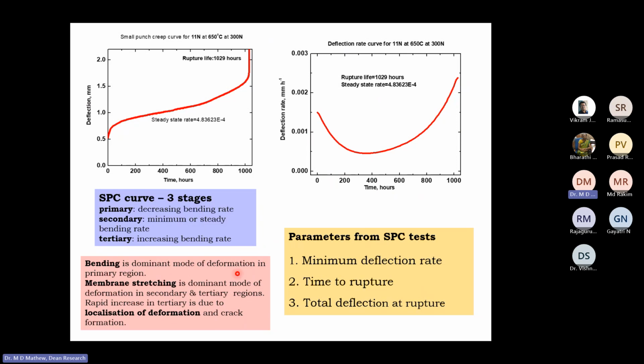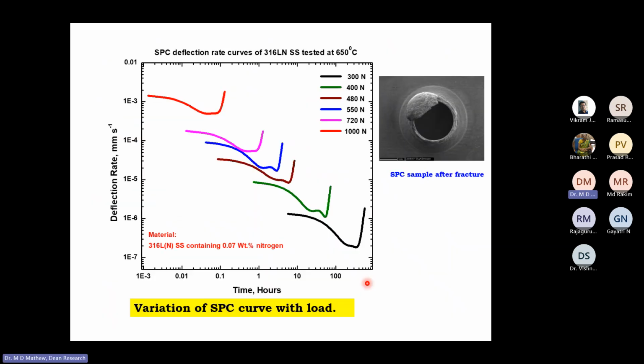As I mentioned, bending is the dominant mode of deformation in the primary region. Membrane stretching is the dominant deformation mode in secondary and tertiary regions, and there is a rapid increase in tertiary due to localization of deformation and crack formation, which leads to fracture. So from a small punch creep test, you are able to determine the deflection rate and also the minimum deflection rate. You can determine the rupture time and the total deflection at rupture. This is how the sample will look once the rupture has occurred.